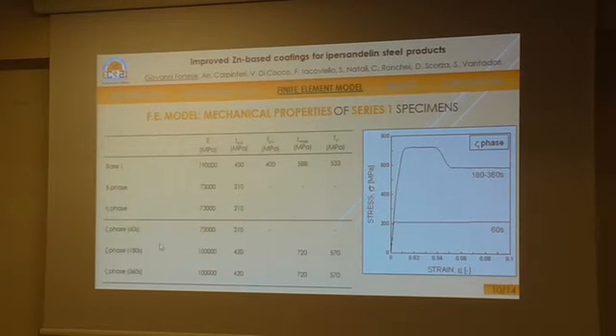The stress and strain curve related to zeta phase is assumed to be elastic plastic for dipping time equal to 60 seconds, and a different curve for dipping time equal to 180 and 360 seconds. Such time dependence curves are assumed in order to take into account the crystal distribution characterizing such a phase, leading to a non-oriented structure which strongly influences mechanical behavior and strength.